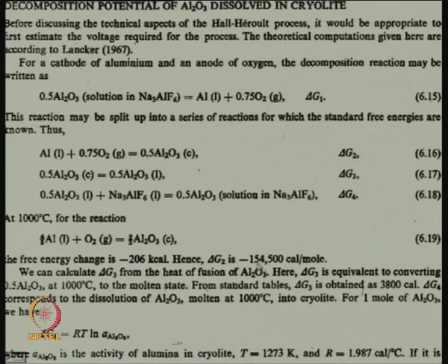So, delta G2 is this. We can calculate delta G3, meaning solid going to liquid, from the heat of fusion of alumina. Here delta G3 is equivalent to converting 0.5 Al2O3 at 1000 degrees to the molten state, and from standard tables you obtain it as 3800 calories. Delta G4 corresponds to dissolution of molten Al2O3 at 1000 degrees into cryolite. For 1 mole of Al2O3 we have delta G4 equal to RT ln activity of Al2O3, because this will depend on the activity of Al2O3 in cryolite.